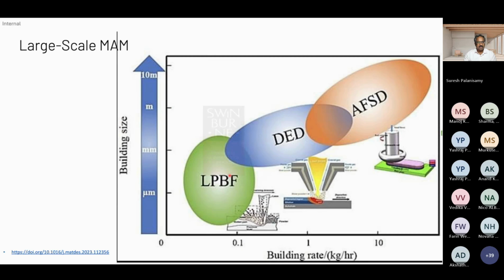When you talk about metal additive manufacturing, obviously powder bed based, this is the powder bed based. So the building rate versus the build size, you can see microns to millimeters. It barely touches meters because the size of the bed determines how big the parts can be. However, DED, direct energy deposition, or blown powder type, can range from millimeters to meters easily. And AFSD, additive friction stir deposition process, as you know, is also a fast, high rate deposition, and it can go up to meters or large scale level. The constraint is again the machine size.